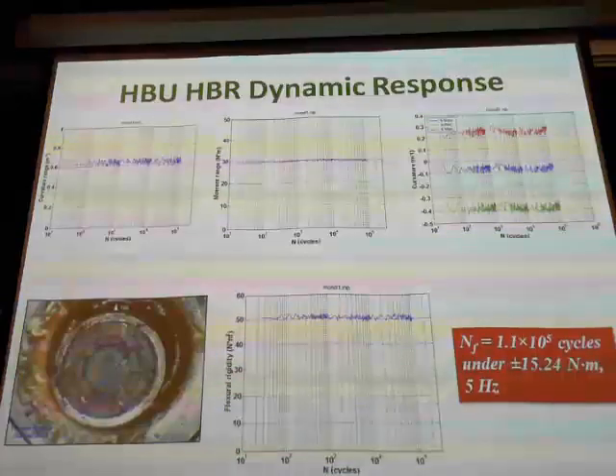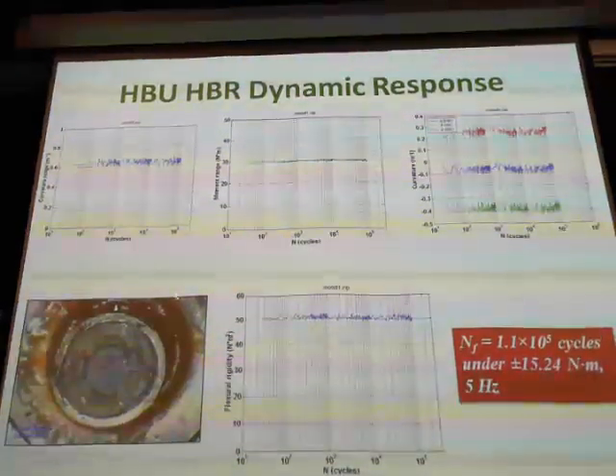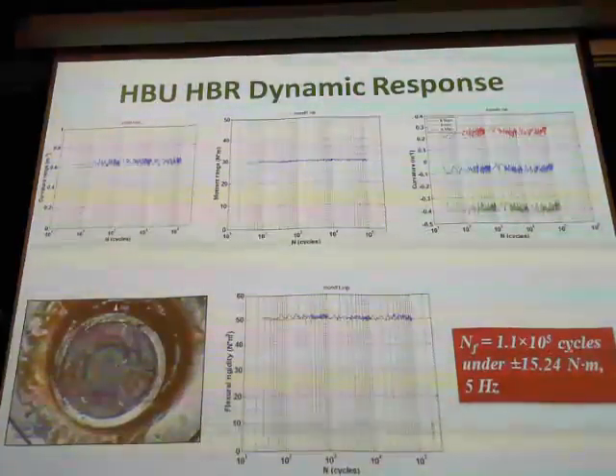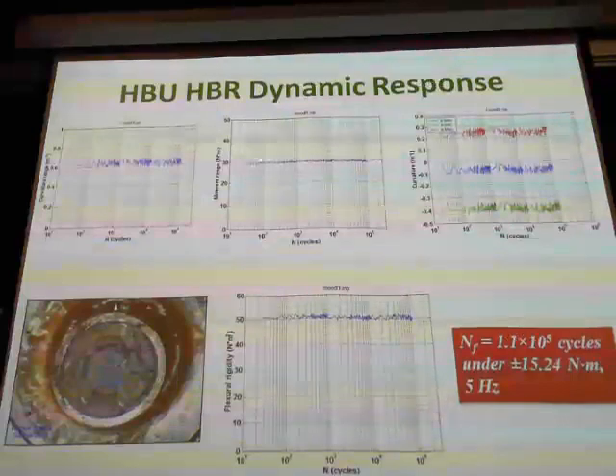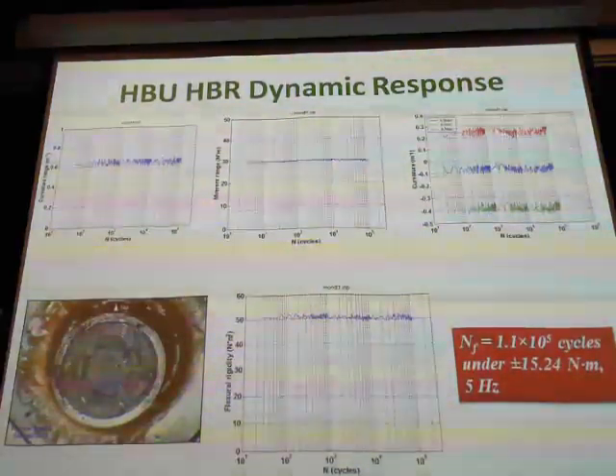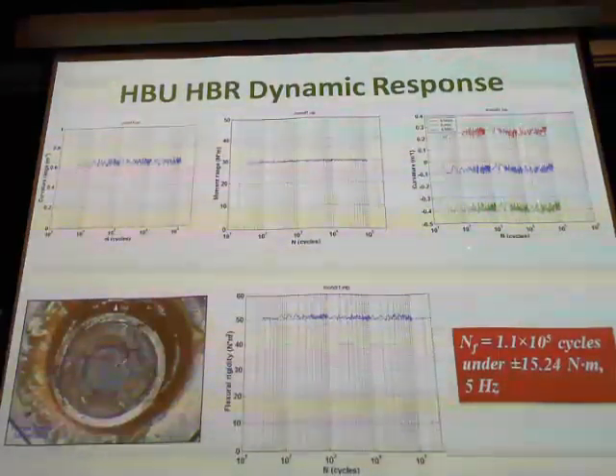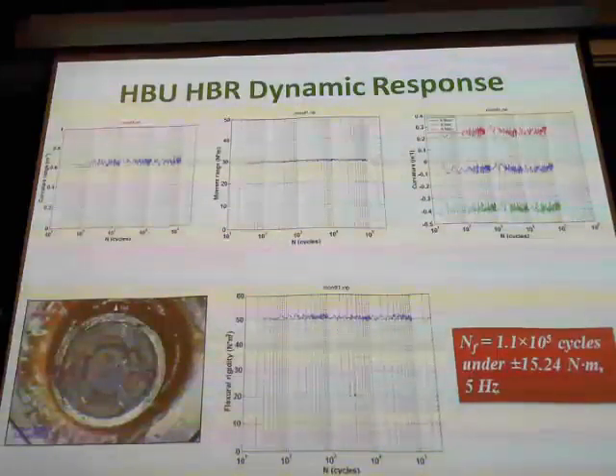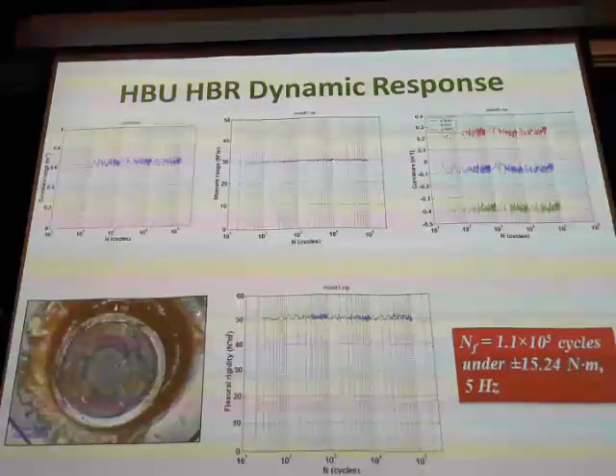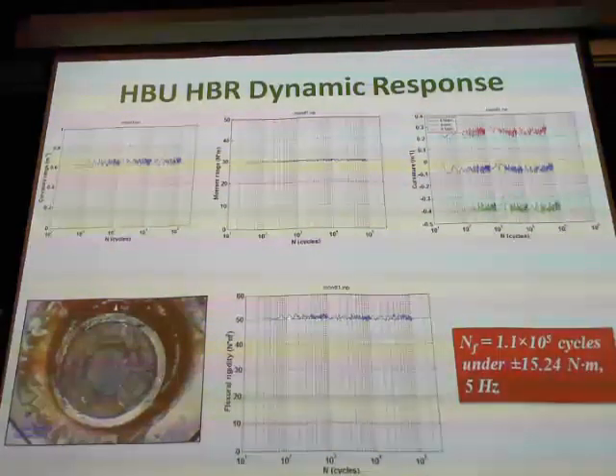I can show you some of the results. This is the curvature measurement. Nothing really changed, pop. This one failed at about 1.1 times 10 to the power 5 cycles. The moment range is constant, plus or minus 15 newton meters. Under the curvature, you can see the positive and negative curvature are different. The reason is that on the tension cycle and the compression cycle, your material responses are different. And flexural rigidity really did not change until it popped.